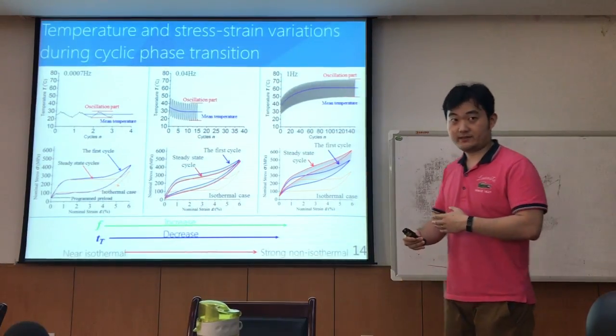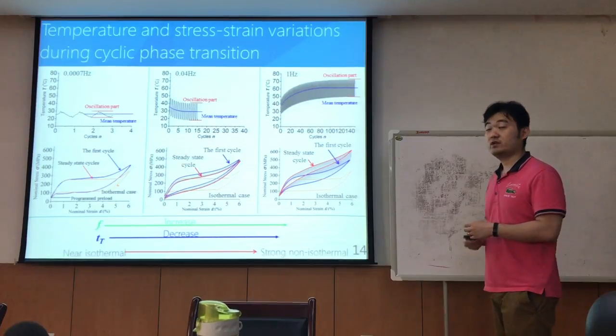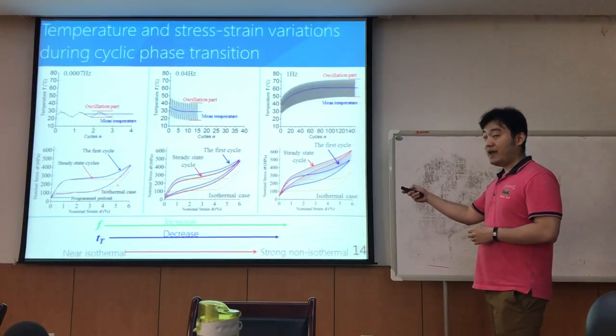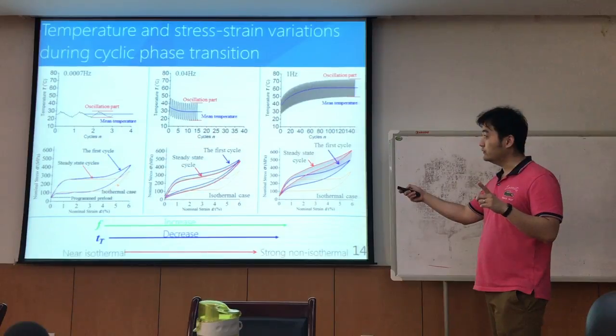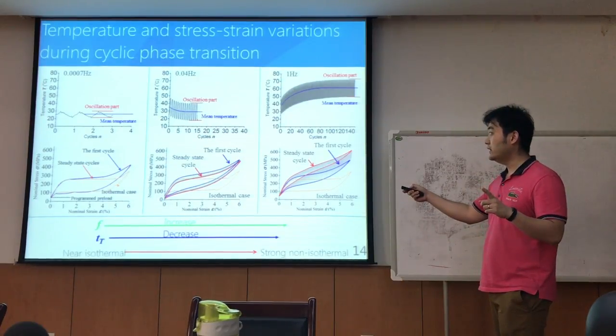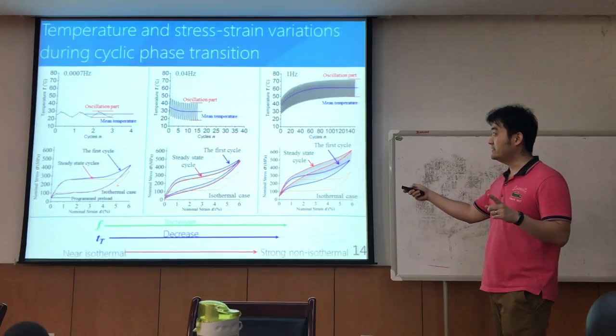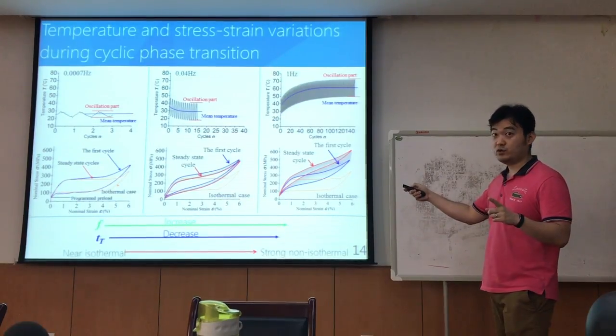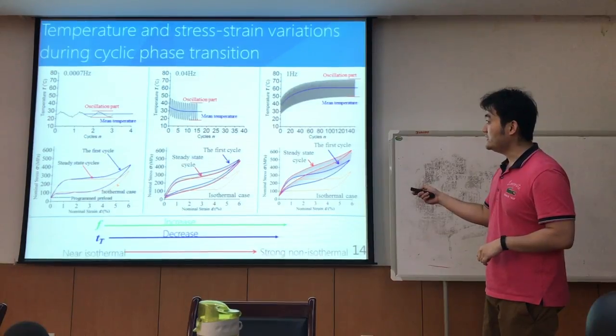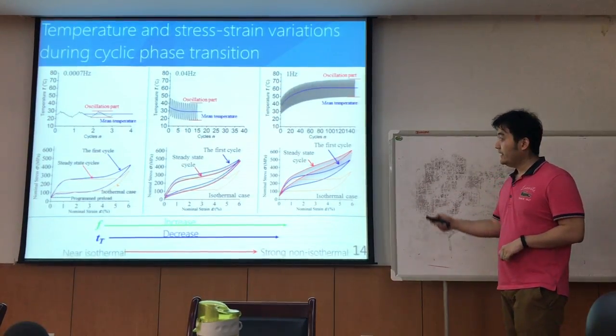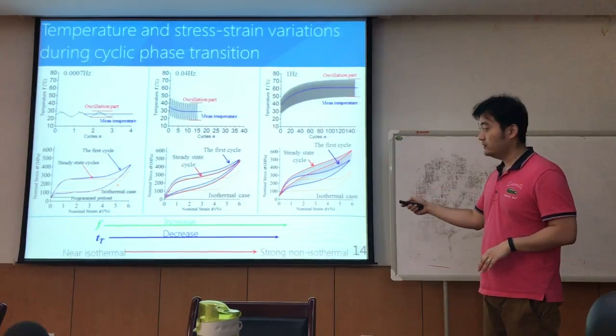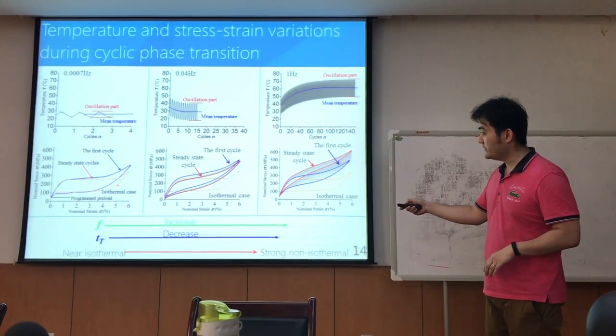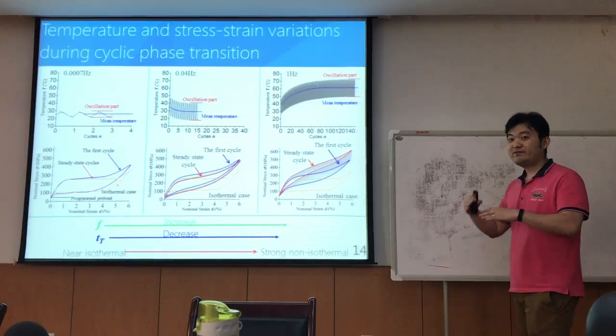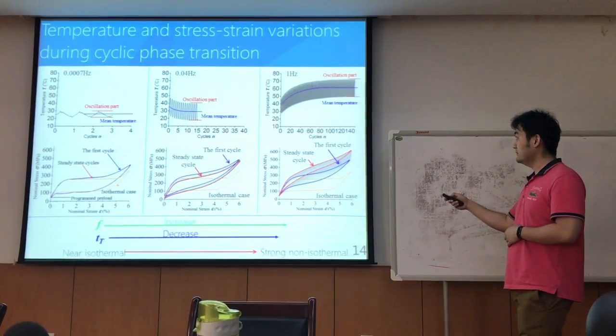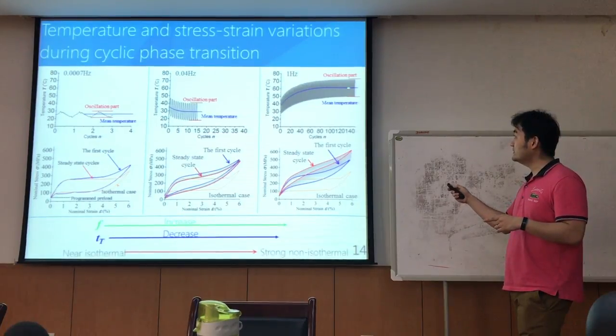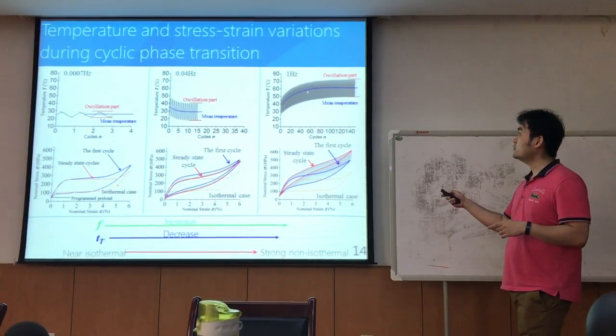But when we increase the loading frequency, first, the mean temperature will drop from a higher level to a lower level. And the temperature oscillation will become much more significant, to about 20 degrees Celsius. And as the mean temperature decreases, the stress-strain curves drift down. When we further increase the loading frequency, there is the opposite phenomenon. The mean temperature will increase.